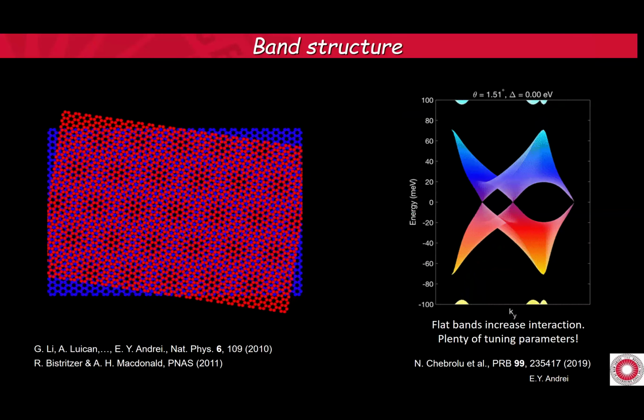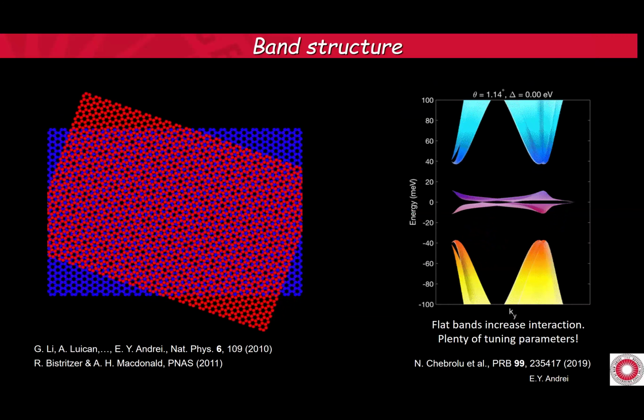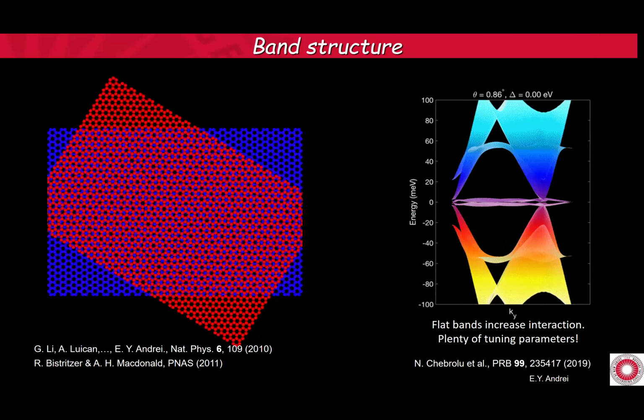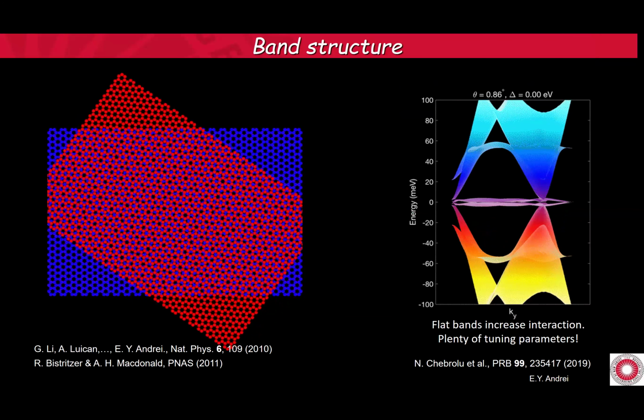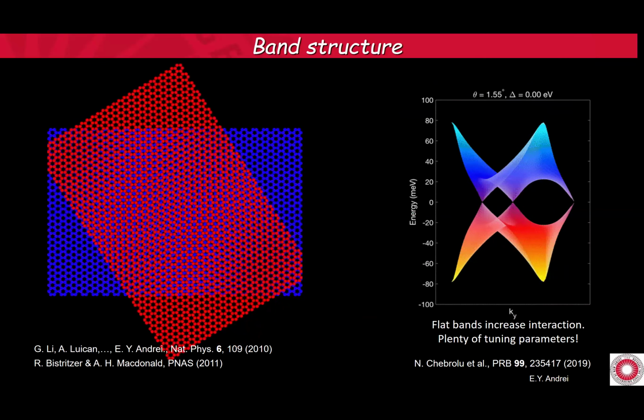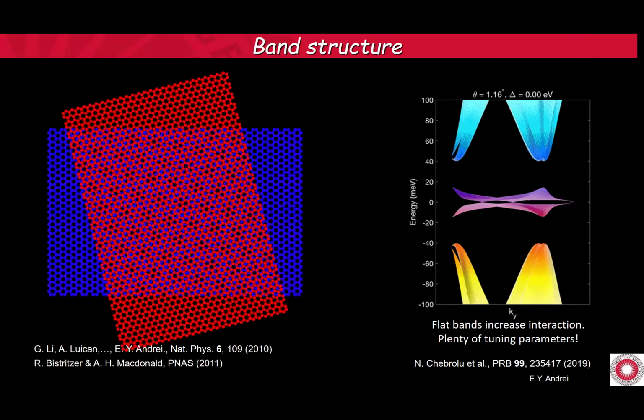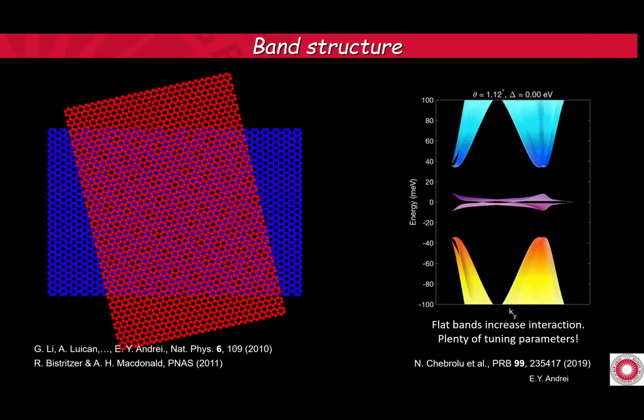Okay, so this is a calculation of the band structure, and you see when you hit 1 degree, you get a flat band that is separated from the remote band. You see the twist angle runs here. And at 1 degree, you get this beautiful flat band.